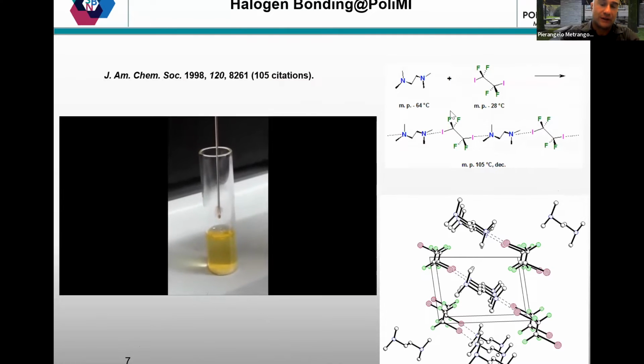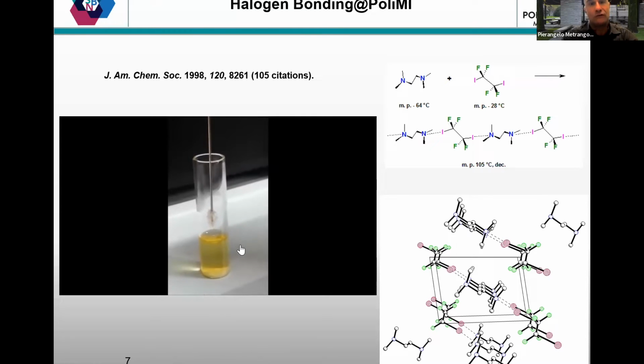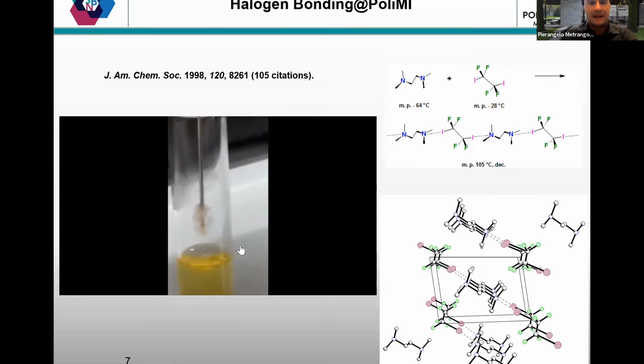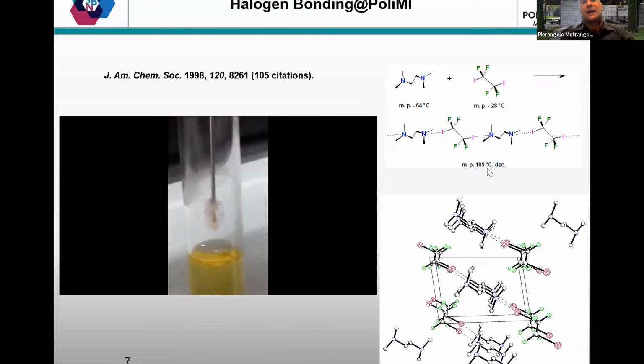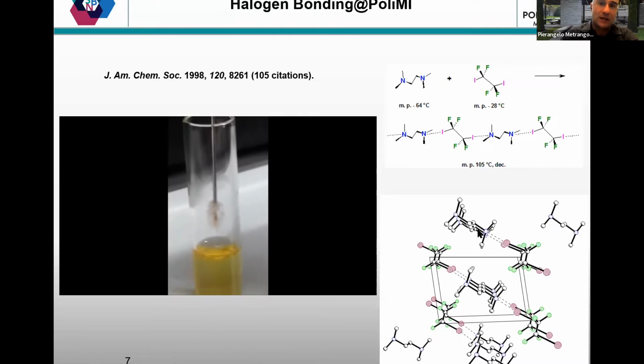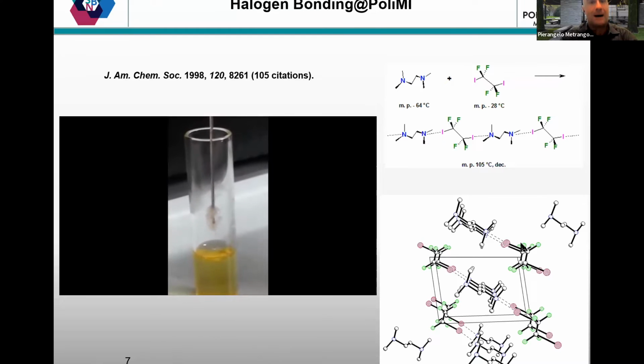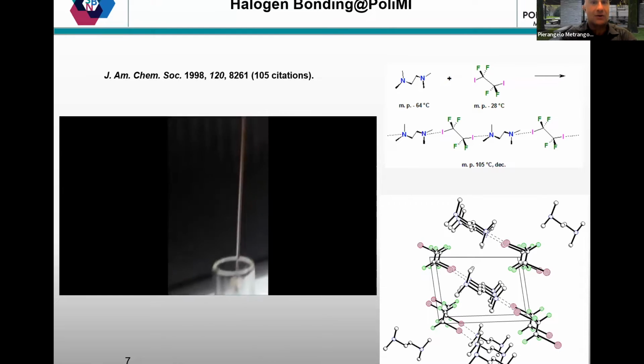diiodotetrafluoroethane with this diamine. So the amine is in the vial, the diiodotetrafluoroethane is in the needle, and as you can see, the two compounds, already from the gas phase, mix, forming very beautiful single crystals melting at more than 100 degrees. And this was our first halogen bonded co-crystal, where, as you can see, two liquids form a high melting solid by just interacting through halogen bonding.